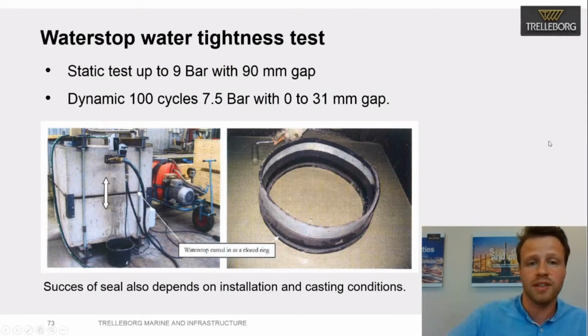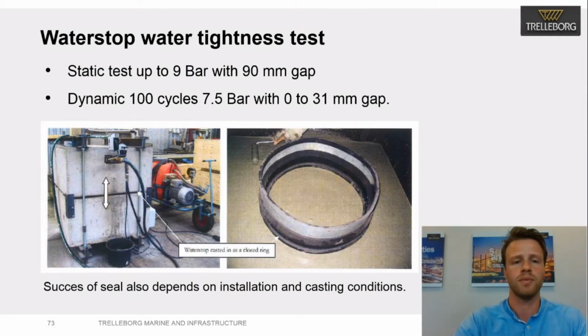Waterstops are also tested for how they perform. We did dynamic cycling tests and static tests up to 9 bar. We poured these Waterstop rings inside concrete blocks, and we performed different ranging movements while also increasing the pressure up to 9 bars. We wanted to see what the failure mechanism was and when it started leaking.